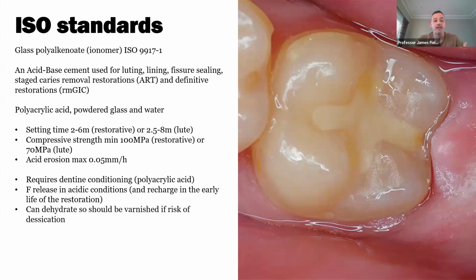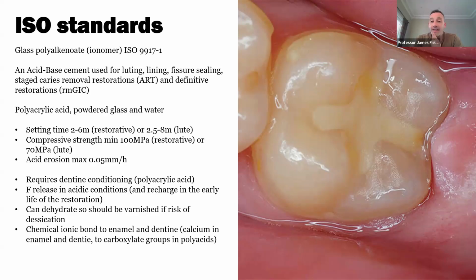And of course, it's a cement, so it can dehydrate. And if it's in a particularly aesthetic area, then it should be varnished. A lot of people don't do that anyway. But really, if you're going to have the mouth open for a long period of time and placing glass ionomers, then we should consider applying a fluoride varnish over the surface. And unlike the other materials, glass ionomers form a chemical ionic bond to enamel and dentine. So it's the calcium in the enamel and dentine which is bonding to those carboxylate groups in the polyacids. And again, these standards stipulate that the bond has to reach a certain threshold in 15 minutes, which optimizes over the next 48 hours.